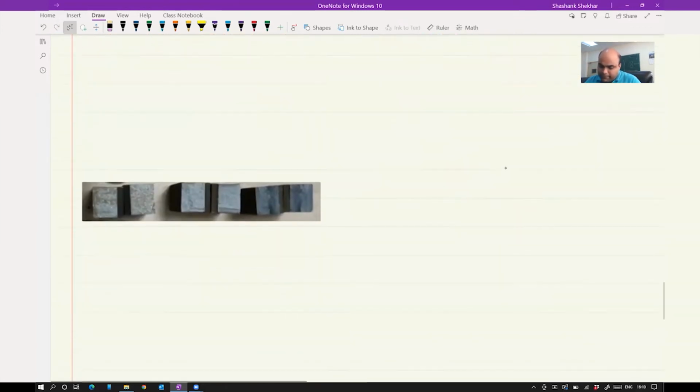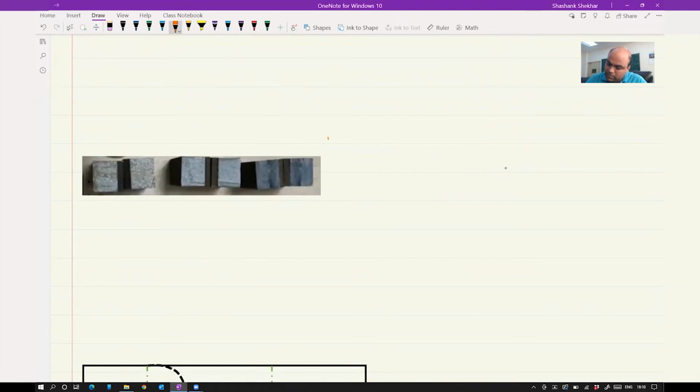And I have here one example. Okay, this was done in our lab, and here your temperature is increasing or, say, decreasing in this direction. So this is at low T. If I mark, say, T1, T2, and T3, so we have samples. Okay, and then what we did was impact testing at three different temperatures. So we did it at T1 and T2 and T3, and then for these three different temperatures we took photographs using a mobile. Okay, and now we are looking at the surface. So here your T1 is less than T2 and T3.